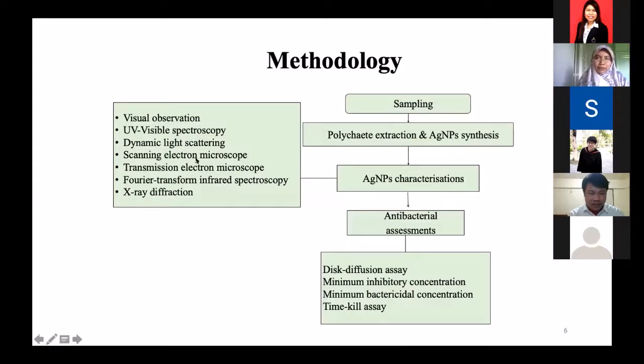So this is our methodology. We need to go and collect the sample, we do the sampling. Then we do the Polychaete extraction and the silver nanoparticle synthesis. Then, to confirm the silver nanoparticle synthesis, we need to do some tests, which we call silver nanoparticle characterization. These are the few methods that we use in our study to characterize the silver nanoparticle: visual observation, UV-visible spectroscopy, dynamic light scattering, scanning electron microscopy, transmission electron microscopy, Fourier transform infrared spectroscopy or FTIR, and X-ray diffraction.